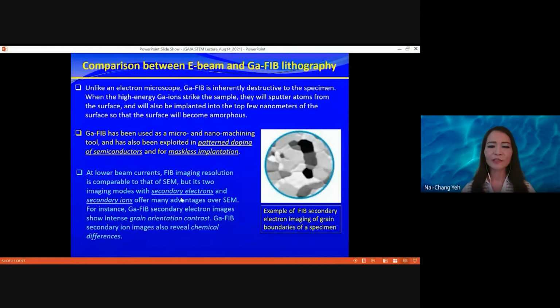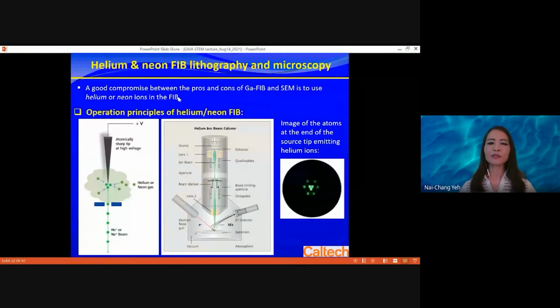But gallium ion beam has additional advantages. It has secondary electrons and secondary ions being scattered off, so you can actually get additional information compared with the electron beam. For instance, this picture shows a sample that has different grains and grain boundaries, and the grain boundaries can be detected by the gallium focus ion beam. But as I said, gallium ion beams can cause damage, and electron beam has more diffraction, so the resolution may not be as good. So it's like in the real world, nothing is perfect. You can try to compromise by using helium or neon focus ion beam, because these are lighter than gallium, so they won't cause as much damage, and they are also much heavier than electrons, so they have much better resolution. So then it depends on what you want to do.